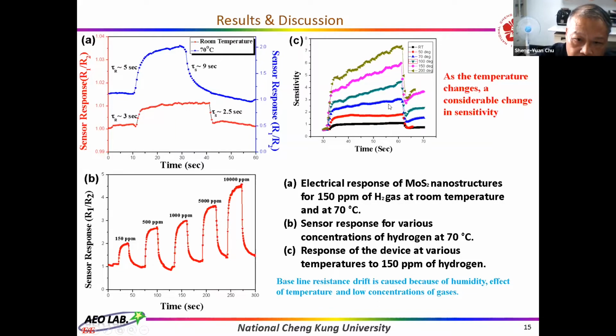The second picture shows the sensor response for various concentrations of hydrogen at 70 degrees. We can see there is some baseline resistance drift, which is caused by the humidity, the effect of temperature, and the low concentration of gases. Figure C shows the response of the device at various temperatures to 150 ppm of hydrogen. And we can see as the temperature changes, there is a considerable change in sensitivity.